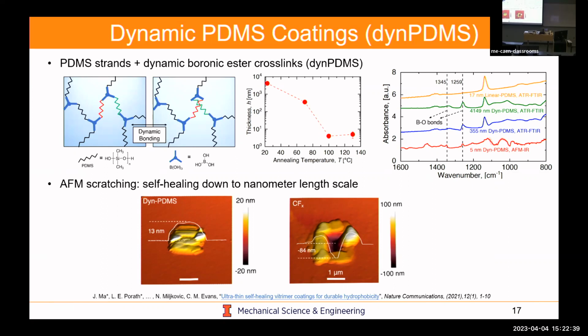And if you look here, this is AFM scratching. So we take a material and we scratch it. And then when we do an AFM scan afterwards, we see that it'll actually self-heal. It'll form a little bump actually. Now, if you look at something like CFX, this is a standard state-of-the-art polymer, your scratch will actually remain on the surface and it won't heal. And so this was good proof that things are working out.